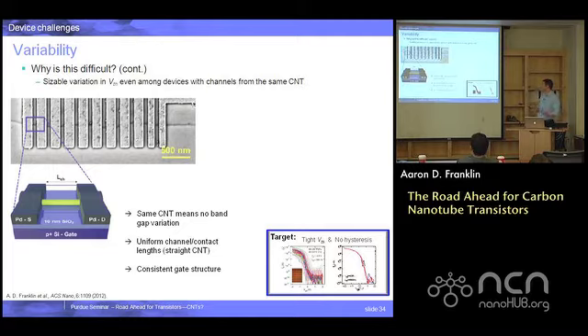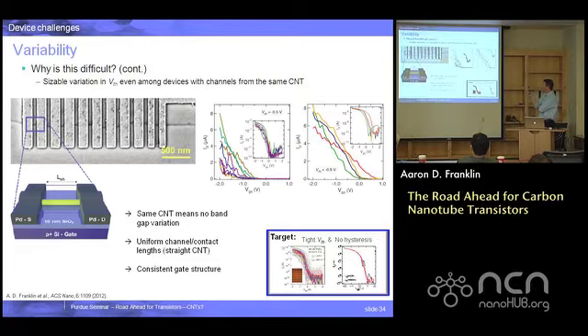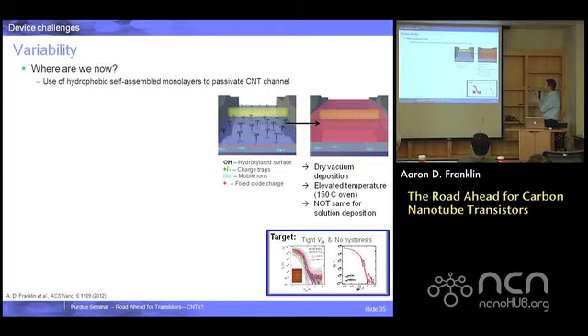So one of the things that we did to try to figure out what the main source of this variation is, we built a lot of devices along the same nanotubes. This is a long nanotube, and this is about 10 devices, and looked at the IV curves. Because we figured, well, if at least we can make sure the diameter is the same and the devices are identical, then we can get a feel for what's being caused by the surroundings. And this is how the curves look. This is from a solution nanotube with 4 devices, and this is from a long CVD nanotube with 8 to 10. And the variation is high, but we wanted to see how much of that is due to the surface and how much of it is due to the gate dielectric, how many charges and impurities are present there.